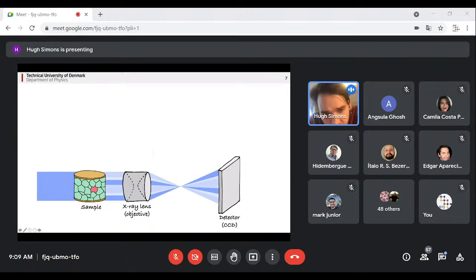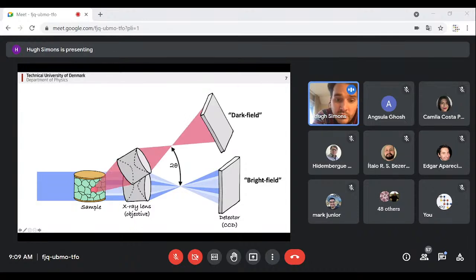But if you want to see just one type of structure inside this, say, for example, this pink grain, what we can do is move this entire imaging configuration into the path of the diffracted X-rays. So this is what we call dark field X-ray imaging. This is exactly analogous to dark field and bright field transmission electron microscopy.